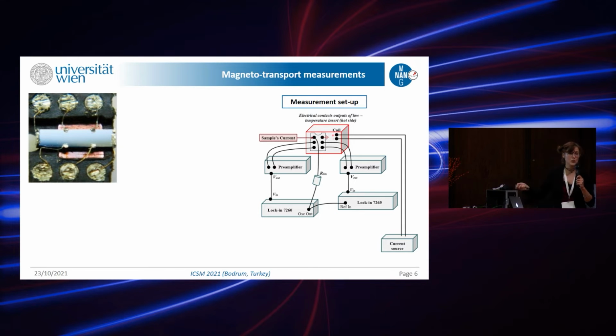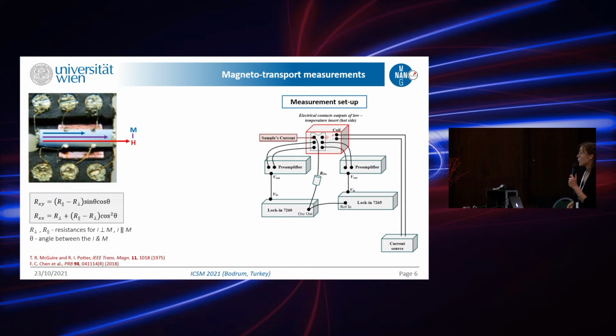Obviously, we had different chips, so we can, for example, change the angle of our sample. In this case, the field was applied, of course, along the long side. Current, obviously, was measured behind these contacts, as is the whole configuration. And when the sample is fully saturated, the magnetization is also along the field direction. What we measure, if we, for example, measure along the